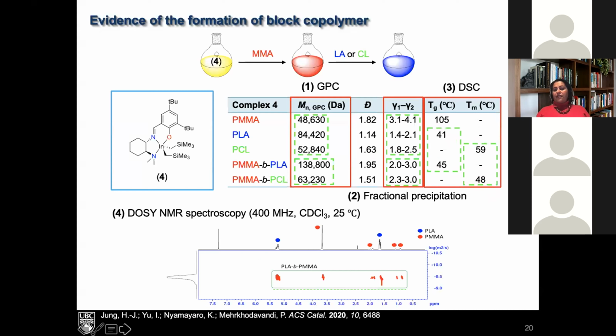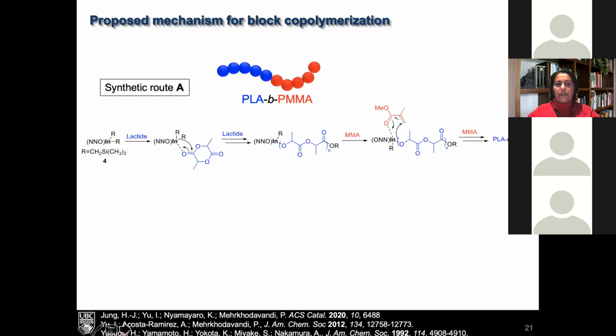And finally, we did in situ DOSY NMR spectroscopy, which allows us to look at the diffusion coefficients of these polymers. And what you can see from the peaks, not very clearly, you have to take my word for it, is that the PLA and the polymethyl methacrylate in solution are actually diffusing at the same rate, and so they're the same molecule. So when you see the peaks in the NMR spectrum, the DOSY tells you that they're diffusing at the same rate. So this really convinced us, and my student June was really pulling out his hair about this, but it really convinced us that in fact this is a block copolymer, which is really exciting.